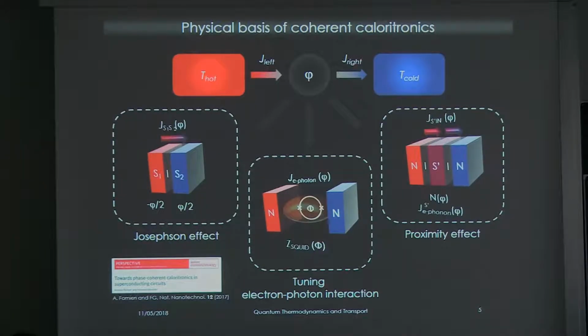What is the proximity effect? The proximity effect deals with conductors that have acquired genuine superconducting properties through intimate contact with a superconducting body. In this proximity effect structure, it is known that the proximity layer, that is S prime in this case, has acquired some superconducting-like properties from this intimate contact, and these properties are very important in the sense that they deeply affect the spectral properties of the metal from the electrical and thermal point of view.